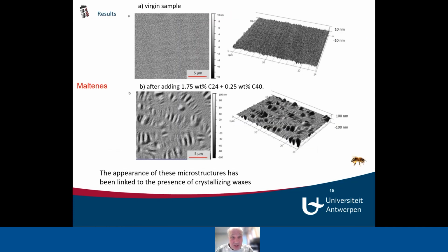In the middle at B, you can see still some wax crystals. So these are pieces of wax which are moving up to the surface, where they then start to form these bee structures. And at the bottom, we also added some filler in order to see what will happen at the filler side, but we couldn't see any effects there. Then we also took some maltenes. If we look at maltenes, we can see no bees, but if we add a wax cocktail to them, we can also generate these microstructures. So we see the crystallization and we see the bee structures occurring at the surface.